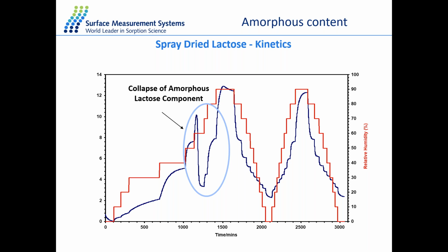So whenever you think of a sample, for example of lactose, the amorphous phase will definitely have a higher surface area, and Mishan is going to talk about surface area later, compared to the crystalline form of the same sample. The mass loss that you see here shows what happens when we move from a sample with a higher to a lower surface area by changing its structure.